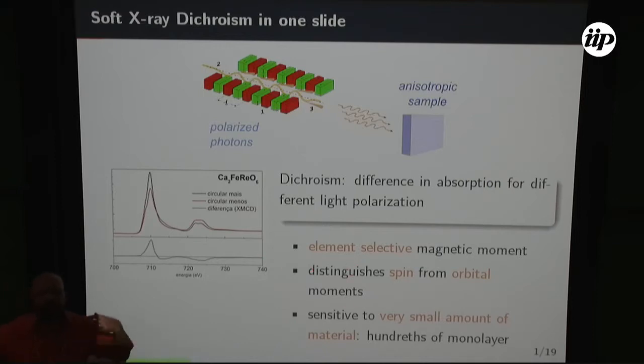But because we are in the soft X-rays, and because we interact a lot with the surface, because it doesn't penetrate a lot, and indeed, this surface sensitivity is more related with the detection technique we use, that I'm going to mention in a moment, this dichroic technique is extremely sensitive to the few nanometers from your surface. So it's very surface sensitive, okay? And these days, surfaces are very important. Interfaces are very important. So you can measure, due to this sensitivity, very small amounts of material. Hundredths of a monolayer.